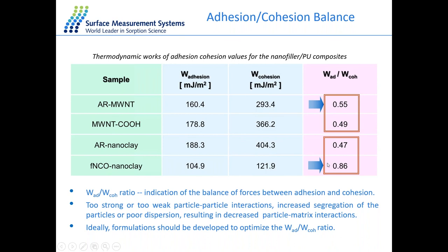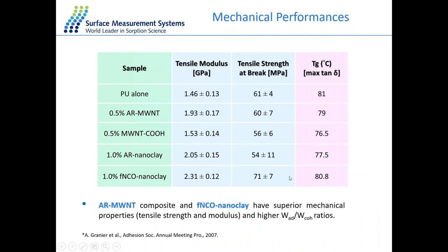So from the IGC result, we can easily predict that the untreated nanotube sample and the treated nanoclay sample may have a better affinity with the polymer matrix in the final composite material. These are just our predictions before we actually make the composite. It's a pre-formulation stage where we make the assumption with the IGC result. And here are the final products. We measured some other properties, like tensile strength, with other techniques.